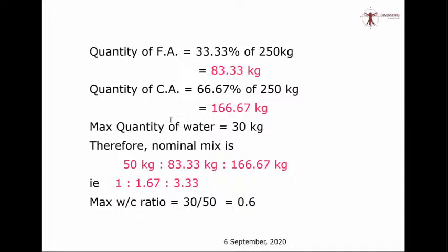If you divide all these values by 50 to make it into a simpler ratio, then it becomes 1:1.67:3.33. So this is the actual nominal mix ratio by weight as recommended by IS 456. It is not 1:1.5:3. Now, if you compare this with 1:1.5:3, you will find that this is a little bit leaner mix. The amount of cement saved here is quite high. If you are using 1:1.5:3, then you would probably use 50 to 60 kg of cement extra per m cube of concrete.